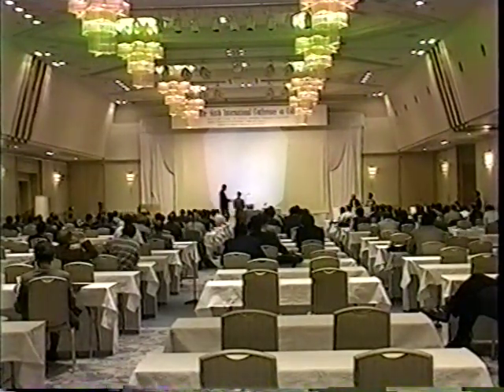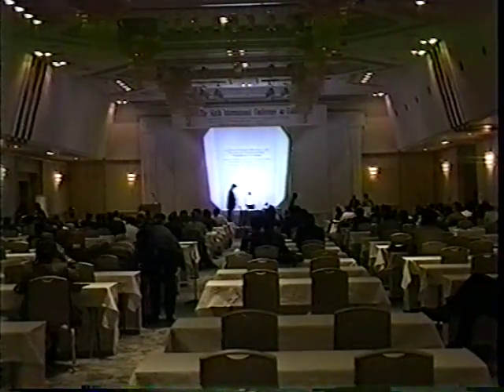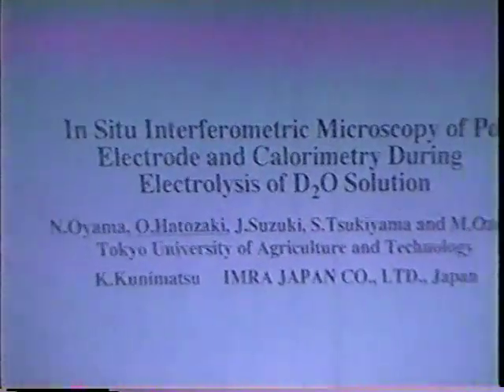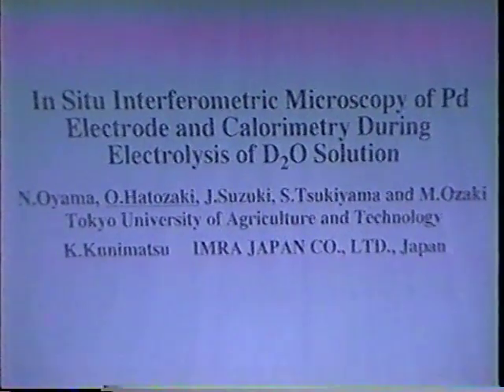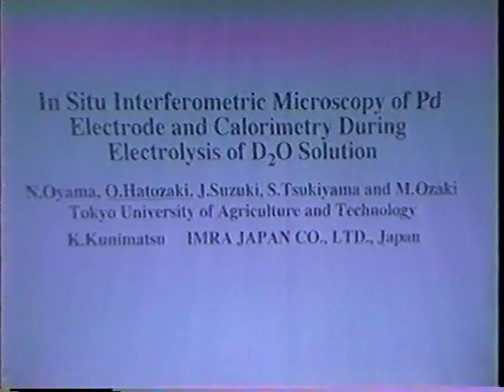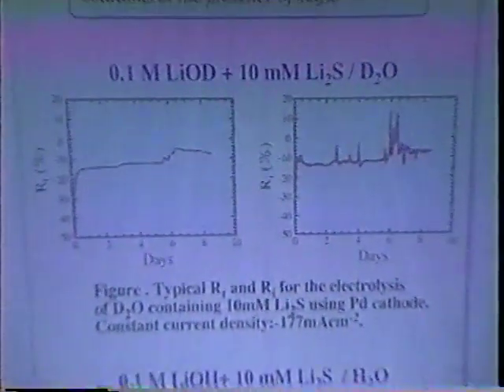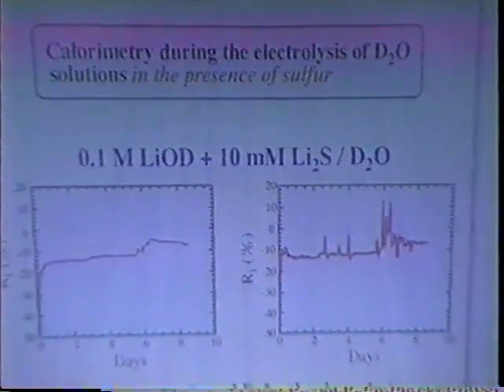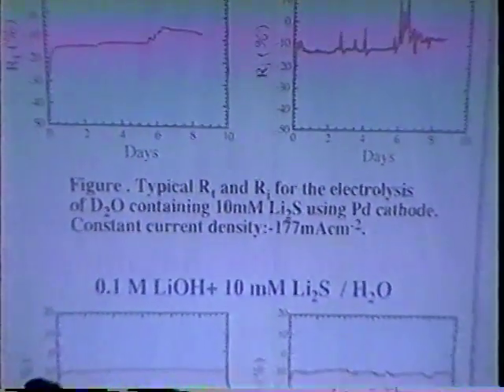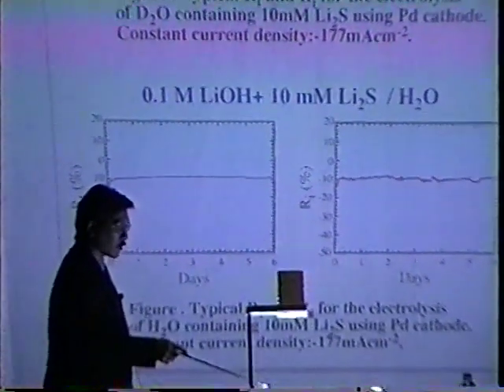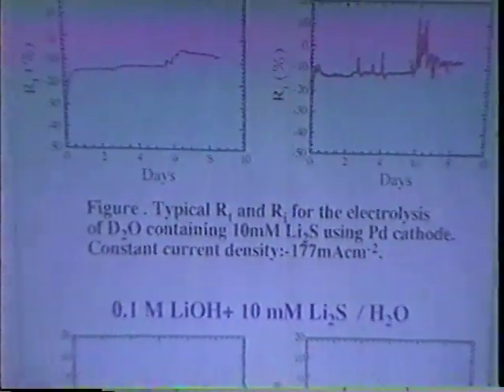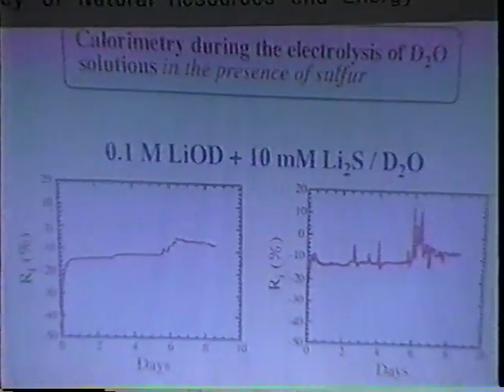Well, yeah. Okay, poster number 30, in situ interferometric microscopy for palladium electrode surface and calorimetry during electrolysis of D2O solution containing sulfur. Oyama, Ozaki, Suzuki, Tsukiyama, Hatozaki, Kunimatsu. We have been studying how substitution of the electrode affects the production of excess heat. We carried out calorimetry in the presence of sulfur. Sulfur ion is expected to adsorb on the electrode surface and improve the absorption of deuterium into palladium. We observed a burst-like heat evolution during the electrolysis of D2O solution containing lithium sulfide, but not for a light water system so far.